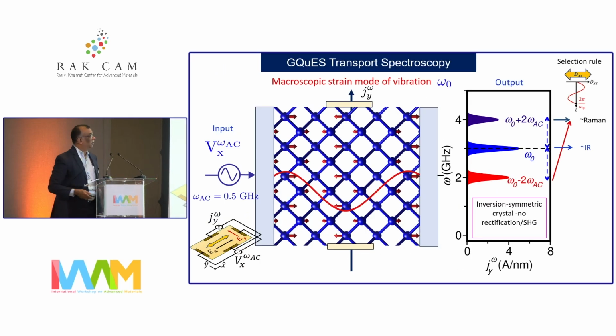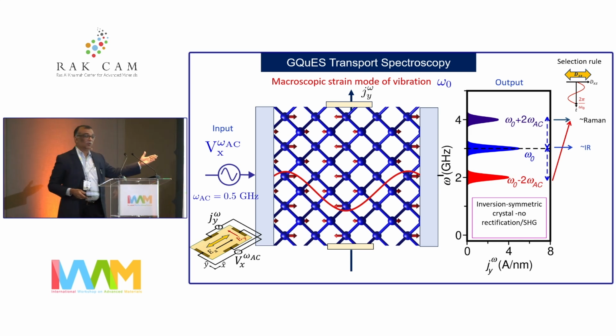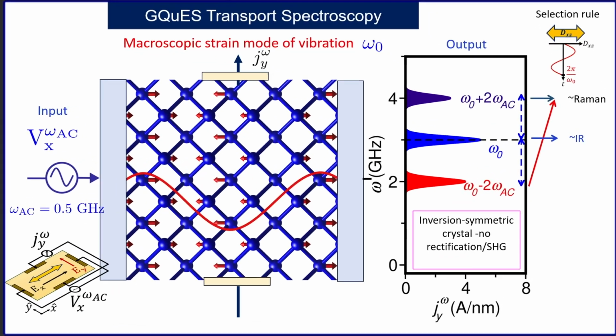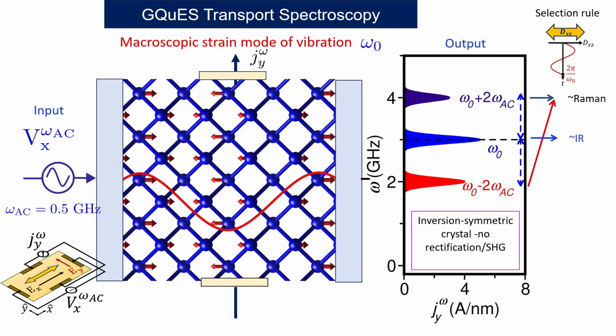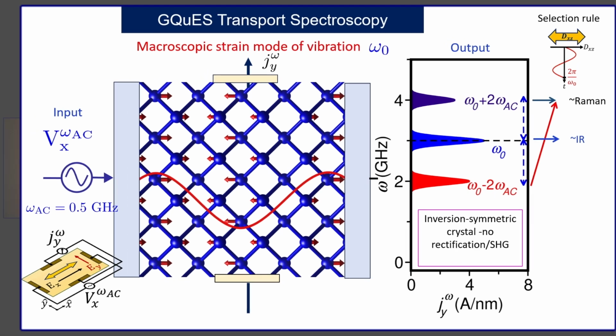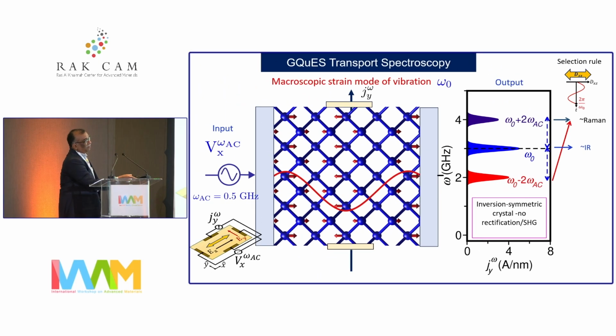So based on that, we first propose a transport spectroscopy, where you have a channel of your material shown here, and there are two electrodes which apply driving field with a frequency omega AC, and one measures Hall current in the transverse direction. And this is our prediction based on the theoretical analysis, that you will see 3 peaks as a function of frequency. One will be centered at the vibrational frequency associated with rectification. And there will be 2 Stokes and anti-Stokes-like peaks, but they are separated by 2 times applied frequency, omega AC.